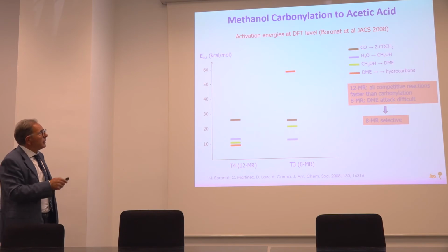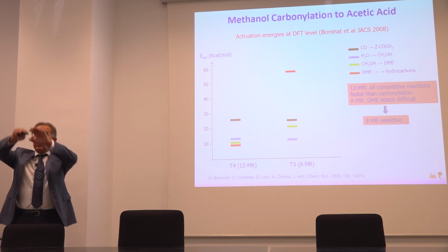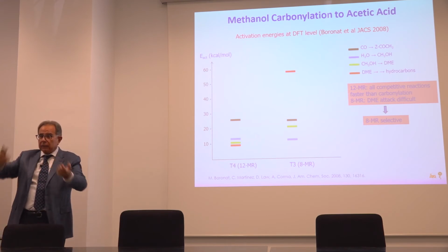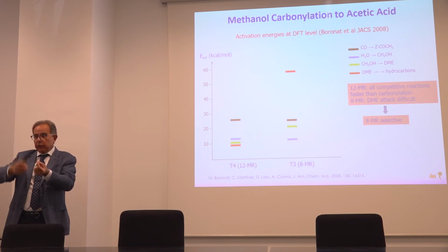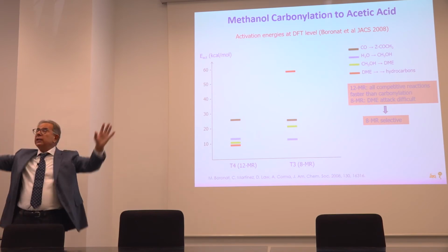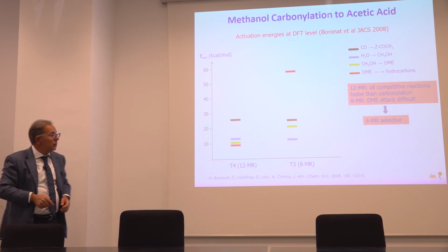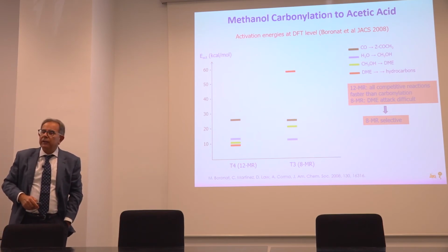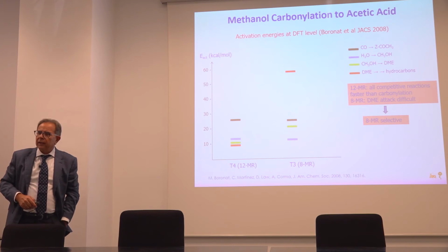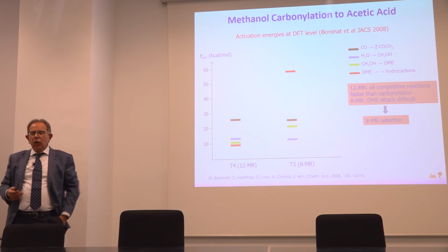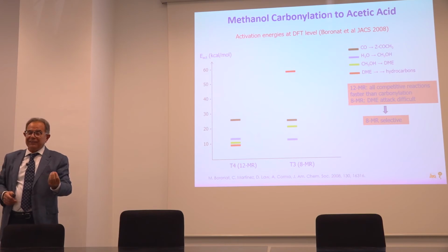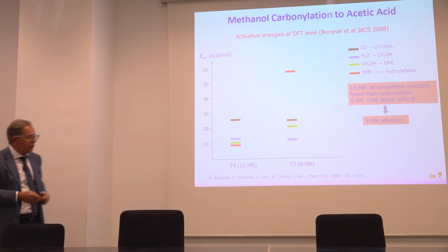However, in the type of calculations that were done there, in which we were not considering at all the interactions with the wall, just the acid and the methoxy and the other molecule, the CO, reacting, without considering any stabilization from the wall, what we saw is that the carbonylation was not the most favorable one. It didn't give the lowest activation energy. So, if one would look only at the zeolite without considering the interactions with the wall, one would be losing the potentiality to explain the results.